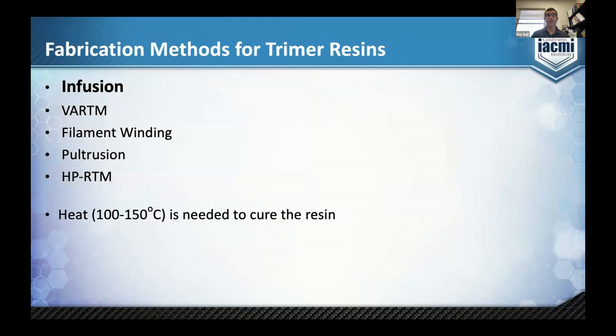So the trimer resin can be processed with a number of different processes. We focus entirely on infusion, but you can also use RTM, filament winding, pultrusion. One of the unique things about this resin is that it needs to be cured at a fairly high, medium temperature, 100 to 150 C. So it's not a room temperature cure.